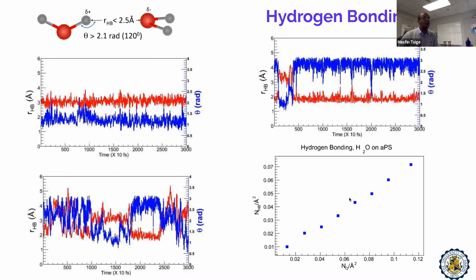Further, we have also looked at how many water molecules were forming hydrogen bonding with a given oxygen atom. For this particular case, for polystyrene oxidized, 99% of the time we have one hydrogen bonding between a water molecule and the substrate oxygen. We didn't see any multiple water molecule forming hydrogen bonding. If we had such a case, in the order of 50%, then we would have expected more like a quadratic dependence instead of a linear dependence. That would have also changed how the contact angle would have changed with the degree of oxidation. So that's a benefit that comes with the simulation, is that we can go ahead and gather those detailed information.